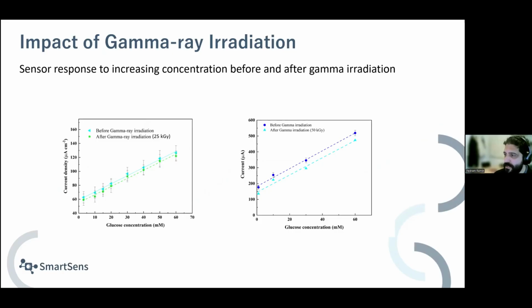Something about the sterilizations that we have investigated. This is with gamma radiation. The figure on the left is with 25 kilogray. So before sterilization and after sterilization with gamma radiation, you can see the slope of the calibration line doesn't change. Similar to the 50 kilogray on the right side. We also have tested it for steam sterilizations. We could at the moment go up to 90 degrees steam, but after that, because we apply different coating materials, this coating melts. It's not very useful at the moment. We are working on different coating material that can withstand temperature up to 140 degrees. But we can for sure sterilize the sensor with gamma radiation.